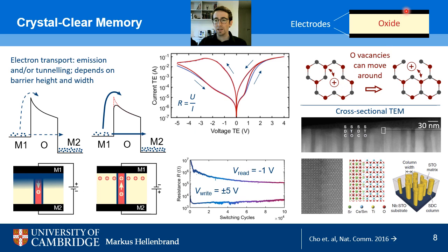So let's say we put a positive voltage to the top contact. This means we push the oxygen vacancies to one side. If we apply a negative voltage to this contact, we draw the oxygen vacancies to the other side. Now the direction of the movement of oxygen vacancies is related to their charge. If you remember from one of the previous slides, inside an atom, the nucleus of an atom carries the positive charge and the surrounding cloud of electrons carries the negative charge.